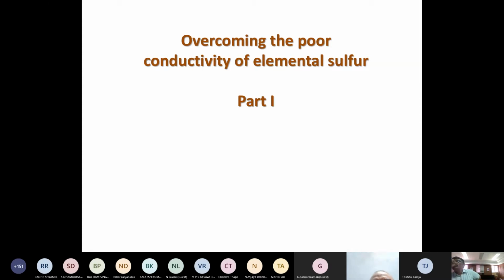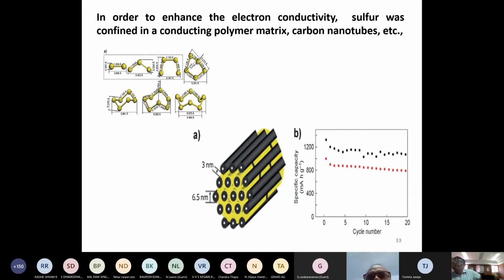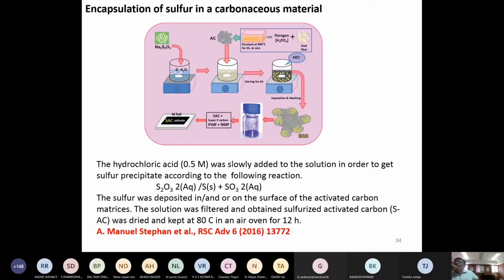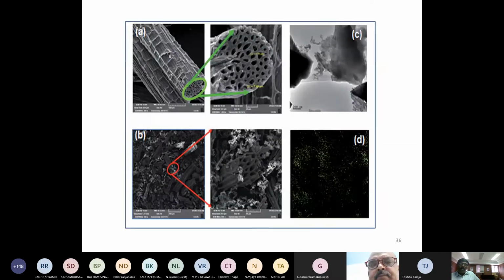So we have taken the first issue; we wanted to improve the poor conductivity of the elemental sulfur. We found that there are several reports where they encapsulate sulfur in carbon nanotubes to improve the electronic conductivity and to prevent the volume change. But that encapsulation of sulfur in CNT or graphene is very expensive and tedious also. So what we have done is we have taken some sisal fibers, treated them with different pore agents, and carbonized them, and this was the pore structure of the sisal fiber. After that, we impregnated sulfur inside, and then we used it as the cathode.